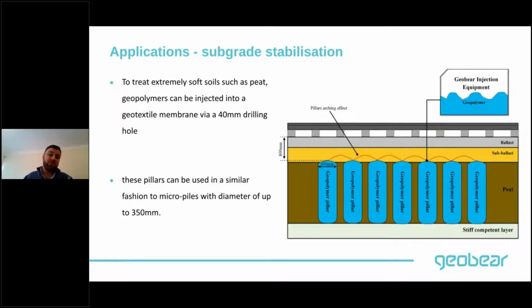For example, we can inject geopolymers into specially made geotextile sacks. And these sacks, as you start injecting into them, will start expanding and create almost like a pillar, a pile, a structure that looks like a pile in that sense. And it will have a diameter of roughly up to 400 mil. And you can install these geopolymer pillars between the sleeper cribs, for example, to almost create a foundation through the peat, and those geopolymer pillars will basically transfer all the stresses from the track and deposit these stresses into a stiff competent layer. So basically bypassing all the load from the peat to the stiff competent layer.